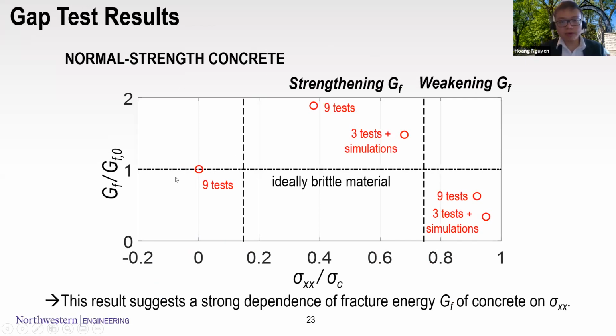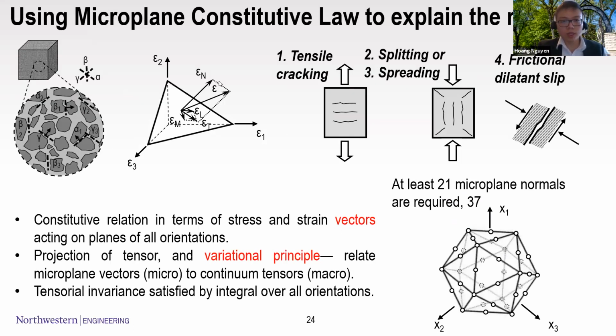So here's the result of the G_F when there's a presence of the sigma_xx here, and we see a non-monotonic trend. At a medium, intermediate level of sigma_xx, you see an increase in the G_F. However, when there's a higher sigma_xx, close to the compressive strength of the material, you will see a decrease of the G_F, and this result suggests a strong dependence of the G_F on the critical stress sigma_xx.